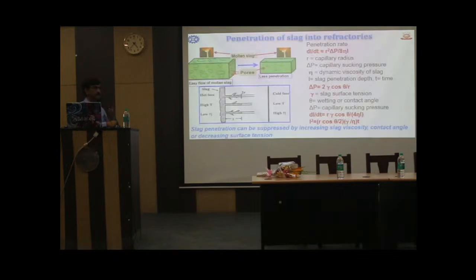Now consider the pore size. For this particular refractory, the pore size is bigger. Bigger pore size means easy flow of the molten salt or molten slag, whatever it may be, in liquid state. But if the pore size is smaller, then penetration will be less. Now, the penetration rate depends on some factors. So this penetration rate is R squared delta P by 8 eta L.